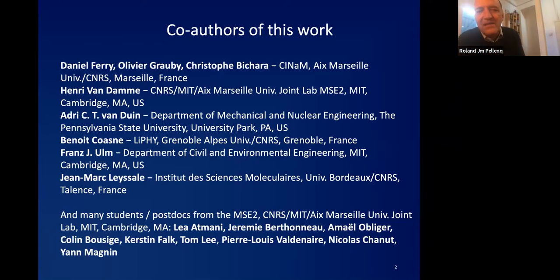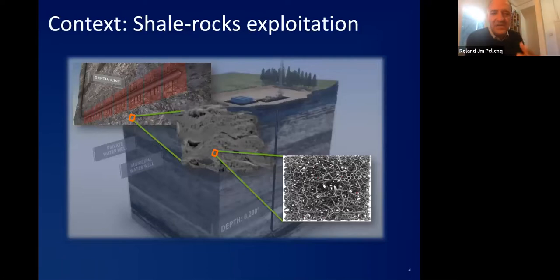And we think we made some pretty good progress in the sense of understanding what it is. So here, on the top left, there's the pipe vertical going down, and at some point you turn horizontal, and this is where you do the fracking jobs. Those are the fractures that you can see in the red regions. And to connect the pipe to those tiny pockets of porous carbon, this is the central picture, where you have this very disordered, multi-scale porous carbon. And if you zoom into the nanoscale, because the central picture is at the scale of microns, you zoom down into the nanoscale, and then you find out, I will show you, that the whole thing is made of a nanoporous carbon with pores at the scale of 1 nanometer.